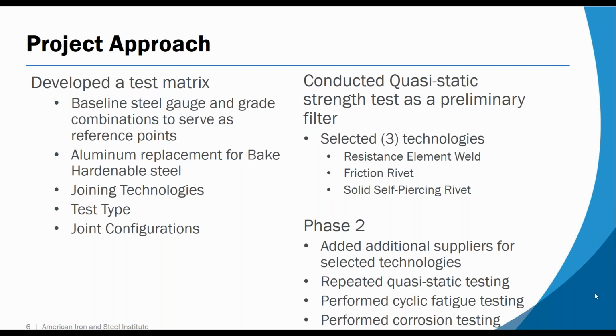selections, and then for each stack we replaced the bake hardenable steel class A surface with an aluminum sheet, and we filled the matrix with all of the currently known joining technologies and a variety of test types, primarily a lap shear and a cross tension, and configured in 2 thickness and 3 thickness with and without structural adhesives. We then did quasi-static testing on all of these joints to establish, relatively speaking, how strong they were compared to a baseline resistance spot weld. Doing that let us filter down to 3 technologies to carry on into phase 2.